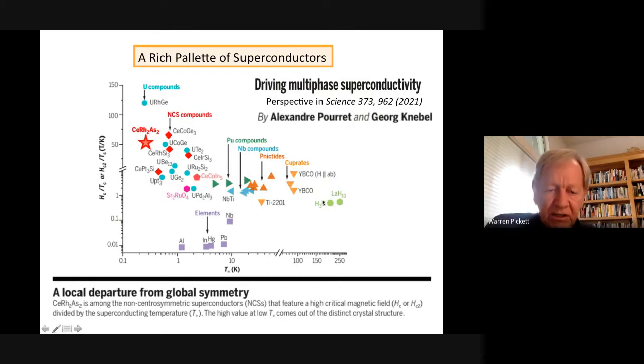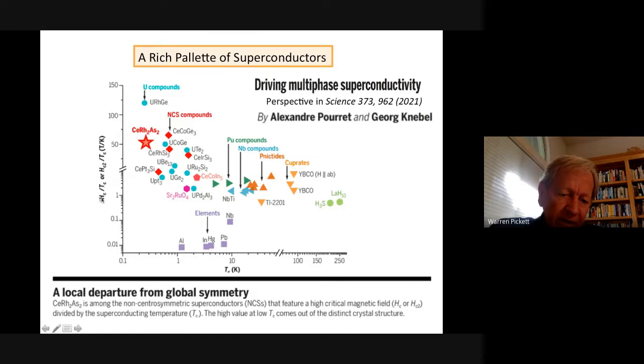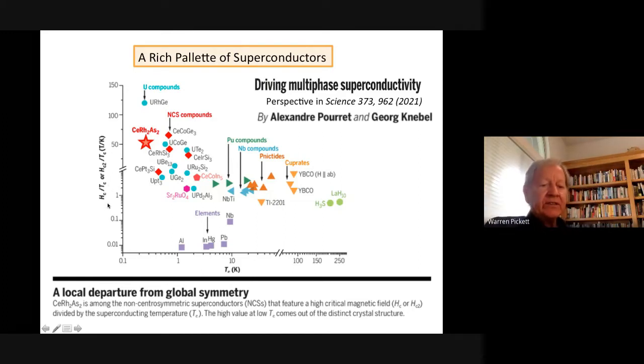This is just to illustrate most of the main classes of superconductors. Here is the superconducting critical temperature on a log scale, 1, 10, 100, a little break here, and 250. And this is the ratio of the magnetic critical field, that's the field which destroys the superconductivity, divided by the critical temperature. Generally speaking, you would expect the critical field to go up as the critical temperature goes up. And that is maybe the overall trend. If that were the case, it would be a linear relationship.